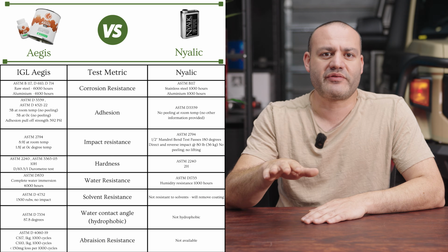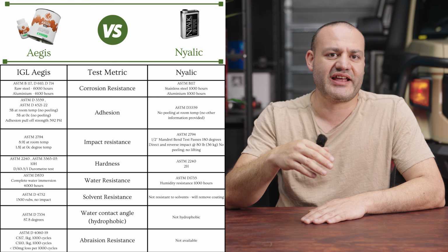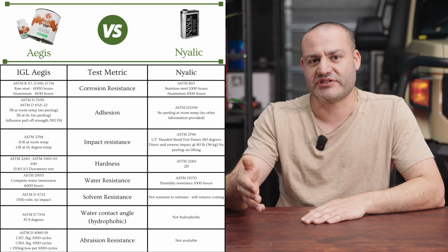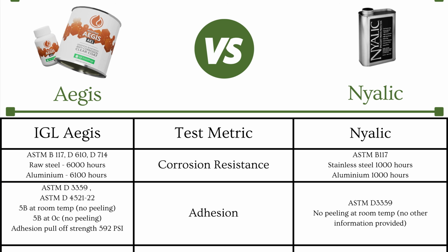Now that we got the technical data out of the way, and thank you for staying with me until now, I'm going to show you how this information is used in the real world. On the screen now is an example to compare IGL Aegis and Nyalic using ASTM test results. I'm not going to go through it line by line, but from the results you can see that IGL Aegis has 6,000 hours of durability for salt spray, Nyalic has 1,000 hours of durability for salt spray, so you can assume that IGL Aegis will last 6 times longer than Nyalic when exposed to salt spray.